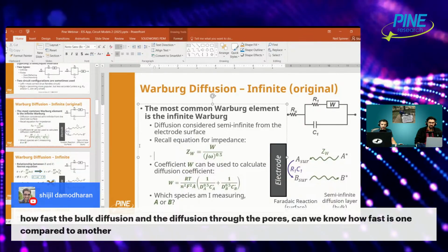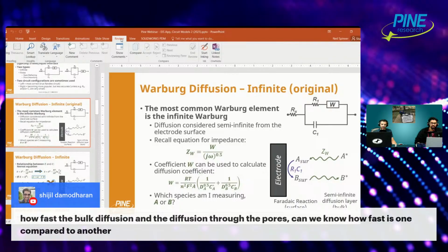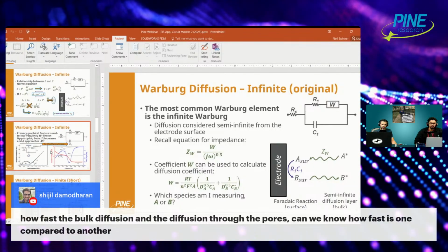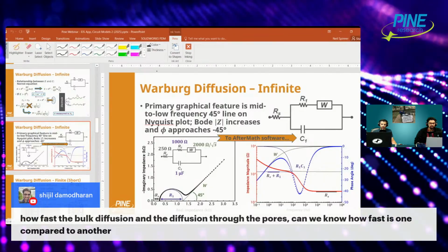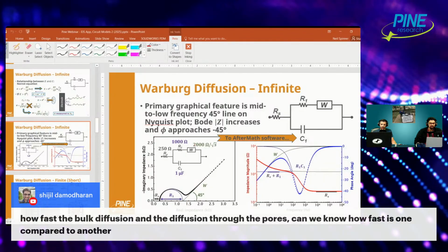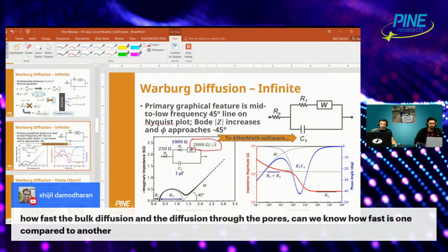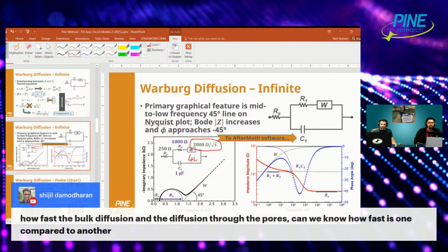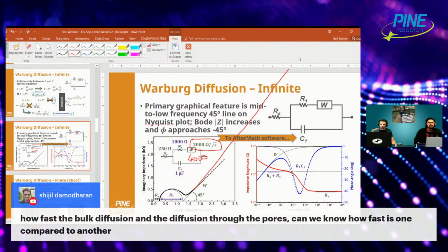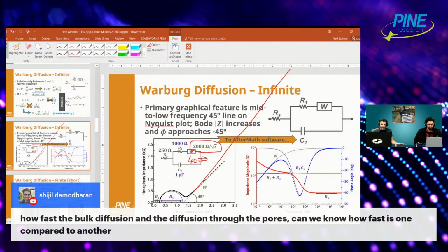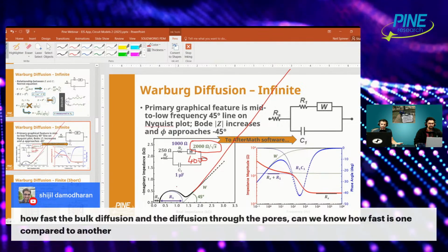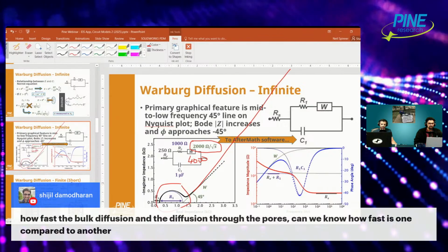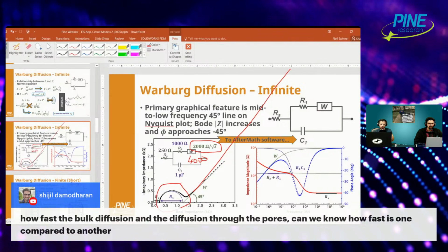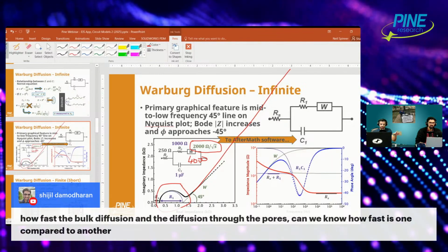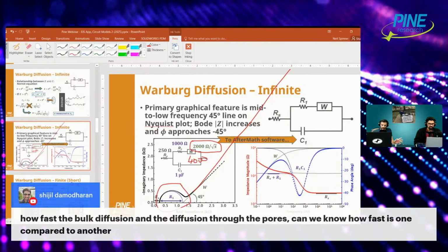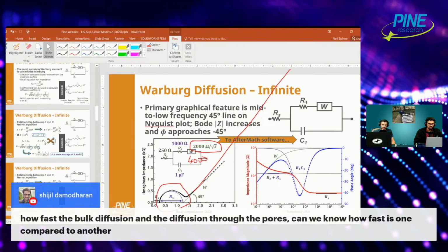The way that manifests on the Nyquist plot, for instance, is a longer tail. So your tail like this is whatever this W is, 2,000. This is just an example of a number here, right? So if I had a W of 4,000, the tail would be longer. So physically on the plot, if the tail goes off really long in comparison to the size of the semicircle, that's indicative of higher Warburg impedance. So worse diffusion, slower, worse, bad, whatever the wording might be. Those are how you might interpret that.